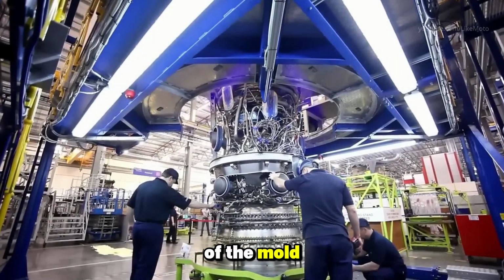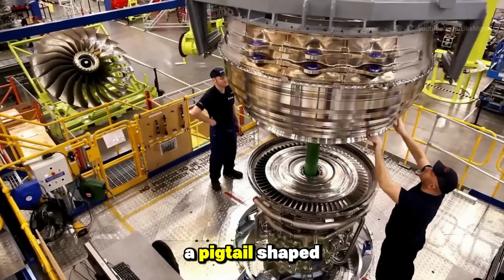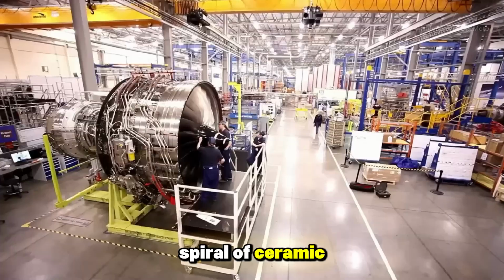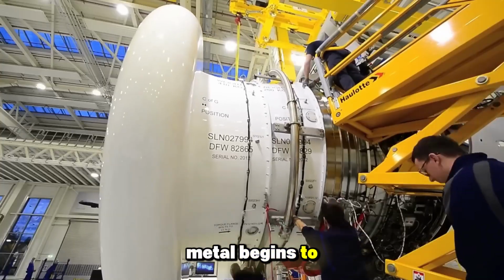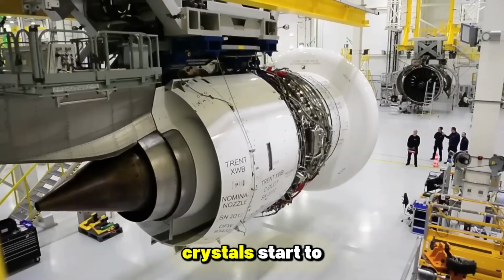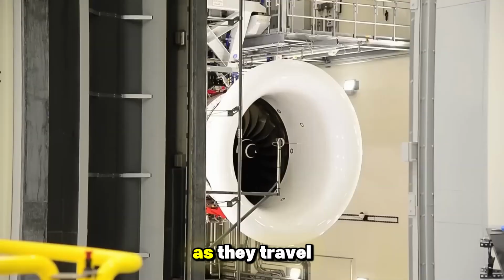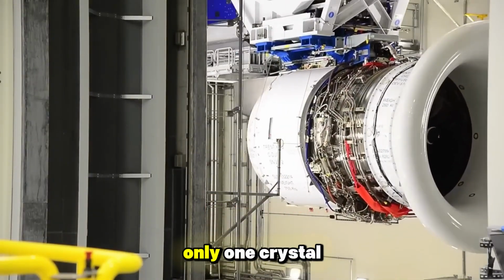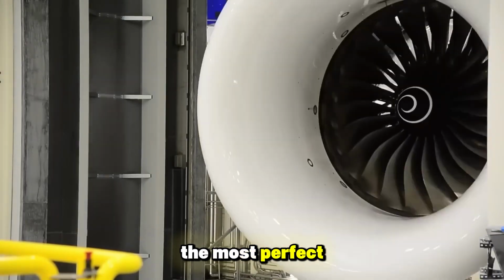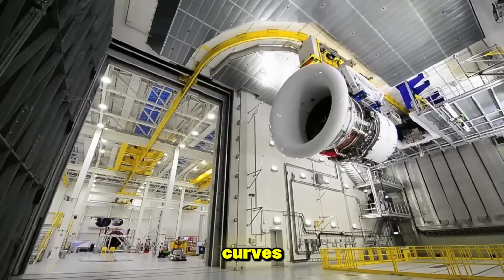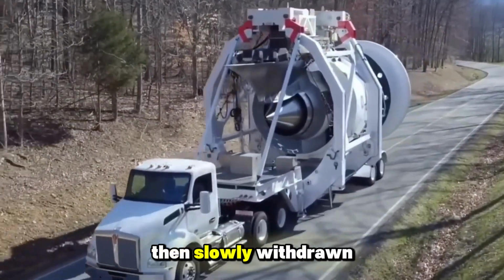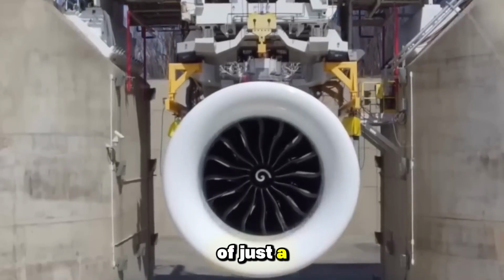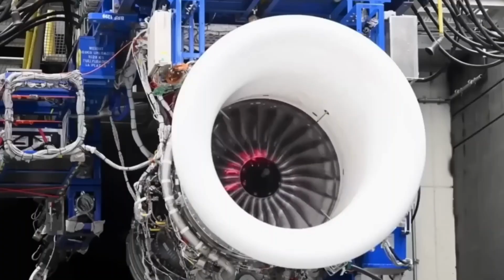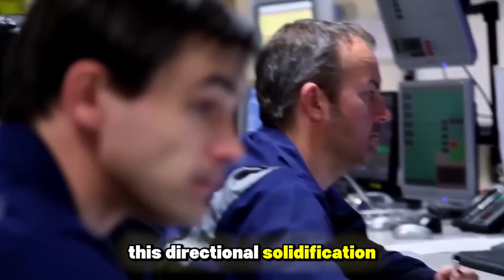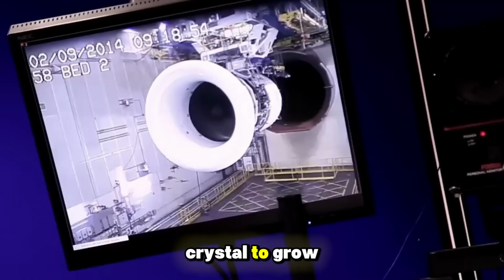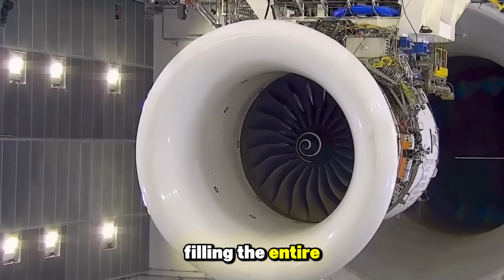At the bottom of the mold is a grain selector, a pigtail-shaped spiral of ceramic. As the molten metal begins to cool, hundreds of tiny crystals start to grow at the bottom. As they travel up the spiral, only one crystal, the one with the most perfect orientation, can navigate the curves. The mold is then slowly withdrawn from the heat at a rate of just a few millimeters per hour. This directional solidification allows one single crystal to grow upward, filling the entire mold.